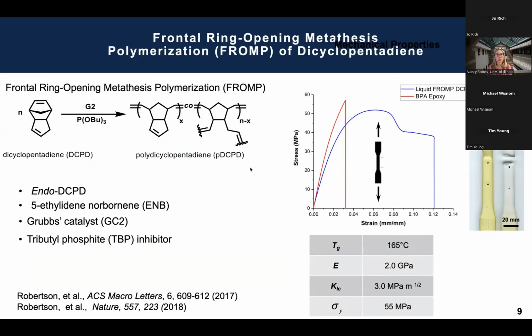It is a cyclic olefin. There's a lot of advantages to exploring this strategy in cyclic olefins. And we are in particular looking at the frontal ring opening metathesis polymerization. We use the word FROMP for short. It's kind of a funny acronym. The monomer is dicyclopentadiene. This is a commercially used monomer. ExxonMobil is now making wind turbine blades with dicyclopentadiene. This just shows the specifics. The initiator that we're using is Grubbs' second generation catalyst, and this inhibitor is also very important for pot life.